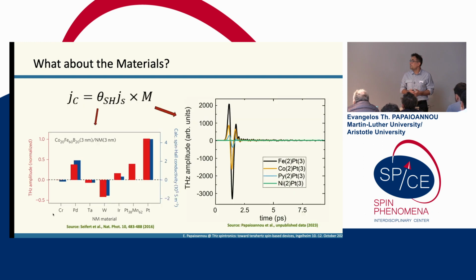But of course you will tell me, Evangelos, materials, what materials? About materials everything is known. And here I show you, also from the Berlin group from 2016, this very nice graphic where, I mean, we all know that the signal we get depends on the spin Hall angle and on the magnetization of the sample. The spin Hall angle depends on the material. It's material dependent on the non-magnetic material, and you see the strength of the signals. Platinum has the first place, tungsten is the second. This is proven many times in the literature.